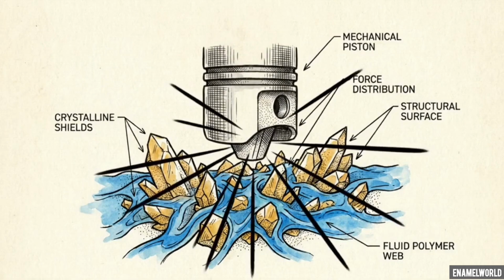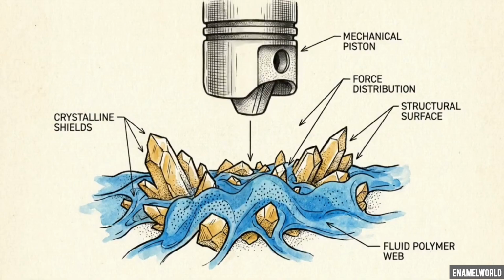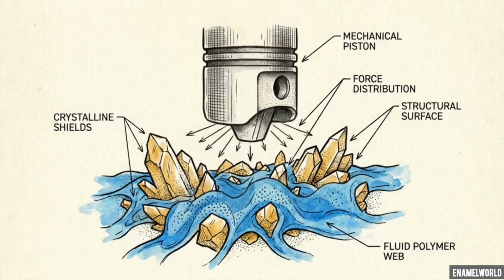They absorb massive compressive mastication forces, preventing the softer polymer network from rapidly wearing away. Heavy metal glasses containing barium or strontium are also included in the filler mix, ensuring the final restoration is radiopaque and clearly visible on future X-ray diagnostics.